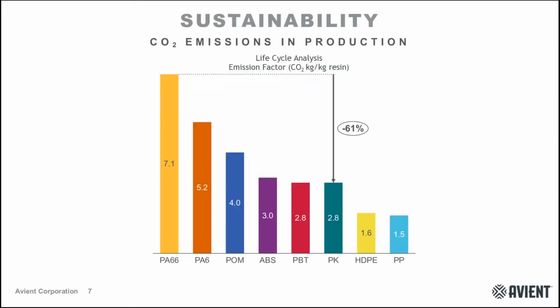So polyketone has a very low carbon footprint compared to many other engineering thermoplastics, in particular nylon 6,6, nylon 6, and acetal. Compared to nylon 6,6, this is a 61% reduction in carbon dioxide, according to a third-party life cycle analysis. And this is primarily due to the low carbon footprint of the monomers, right? We're talking about carbon monoxide and ethylene and maybe a little bit of propylene. And this is going to be more similar to that of a traditional polyolefin. The take-home message here being, with polyketone, you're going to get engineered thermoplastic performance with a polyolefin type carbon footprint.